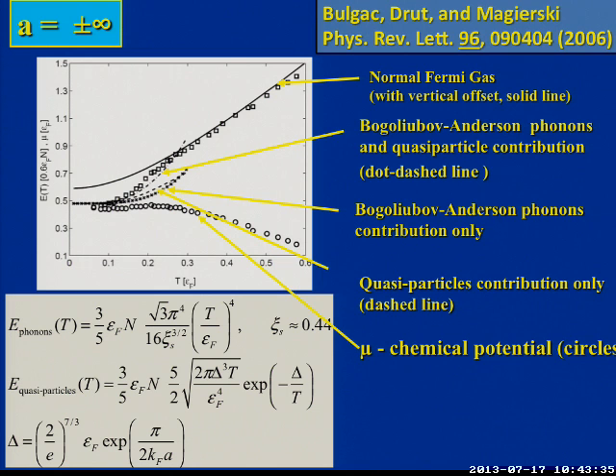So we cannot go to very small temperature to distinguish between the two. And numerically, in this region, they're almost the same. Add them up together, they almost explain it. I'm not saying that this is an explanation, but you see what is probably happening there. So you expect in this system that, at least in this temperature regime, you excite with almost equal probability phonons and break up Cooper pairs.